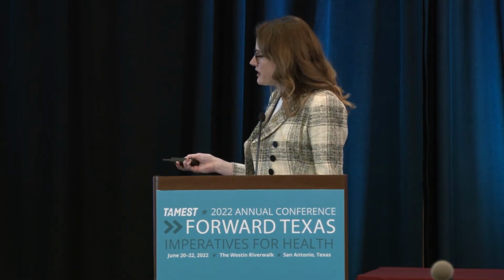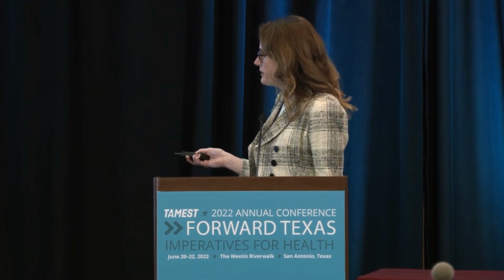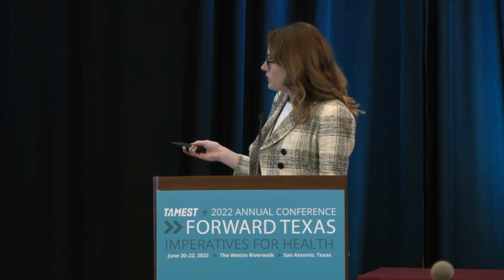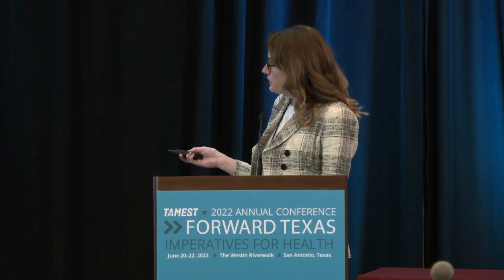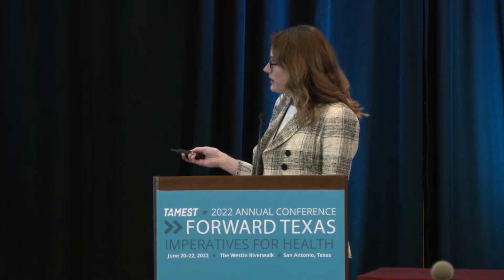Our approach is to use a technique called electrochemical quartz crystal microbalance with dissipation monitoring. We didn't invent the technique, but we've invented and developed a lot of the extensive data analyses that go into analyzing where everything is. So as an example for this talk, I'll just give you one example with PTMA and its anion triflate. So instead of X, it's a triflate. If you transfer or store 1 coulomb of electrons or charge, the mass of the electrode should change by 1.54 milligrams. So if I can weigh that, and I can compare if I get higher or lower, I can tell you if solvent molecules are moving, I can tell you if cations are moving, I can deconvolute what is moving when at a certain state of charge.